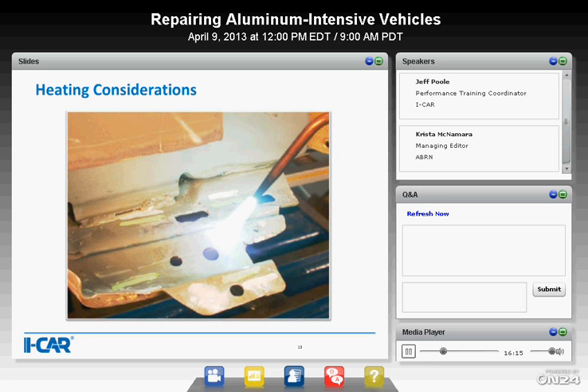So we want to make sure we also monitor that heat. That's very, very critical, using temperature sticks, paints, or a non-contact digital thermometer. Those non-contact digital thermometers, you need to have that adjustment for emissivity, for temperature correction based on the reflective color temperature of the material that we're using. So again, things to keep in mind as we're going through there. Time is not so much a consideration when heating aluminum as temperature is.